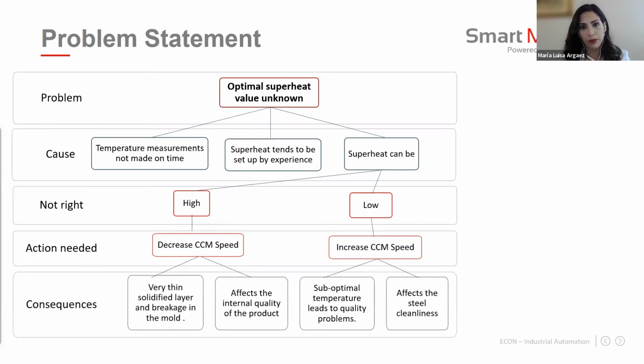On the contrary, when we have a low superheat, it means that the steel temperature is below the optimum for the casting process, and it can be compensated by incrementing the CCM speed. But this can cause non-metallic inclusions. And non-metallic inclusions can compromise the ductility of the solidified product and thus its mechanical properties.